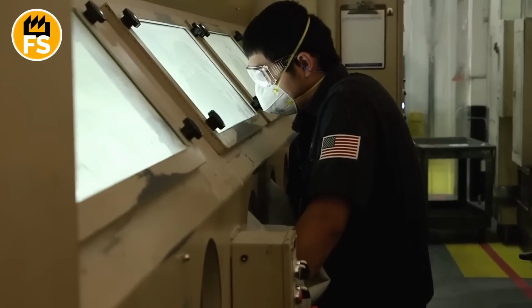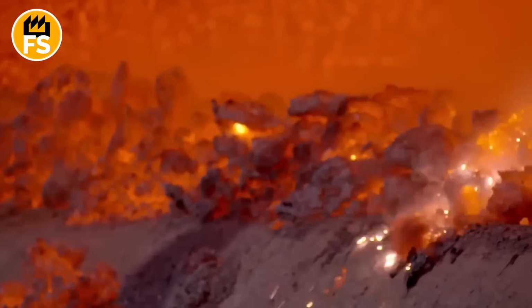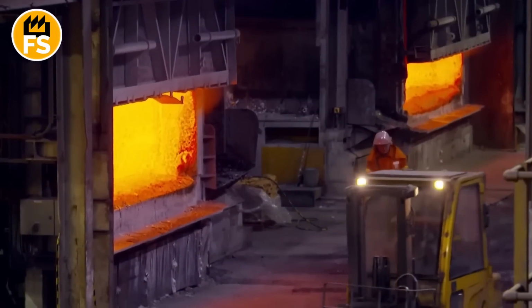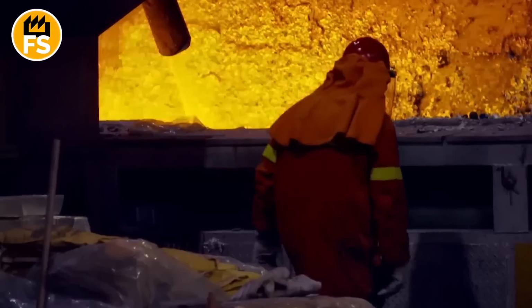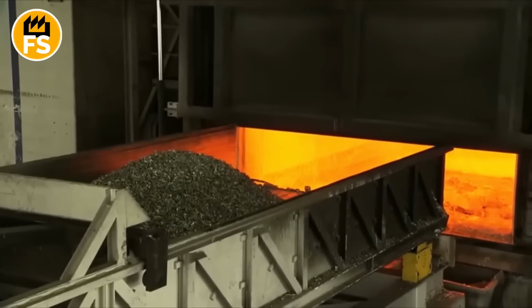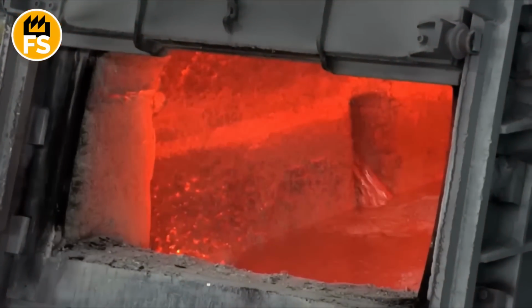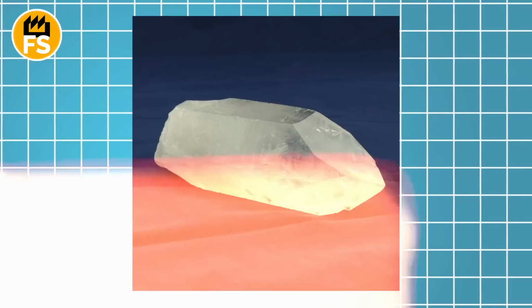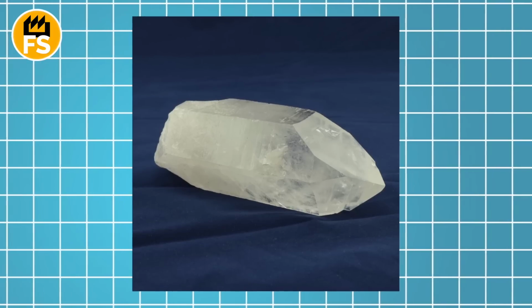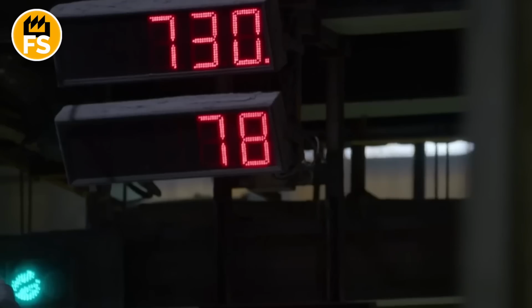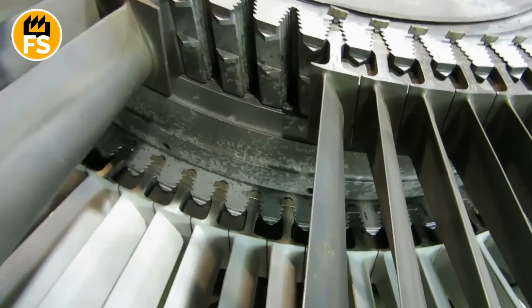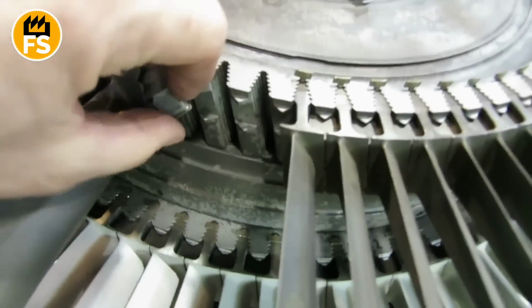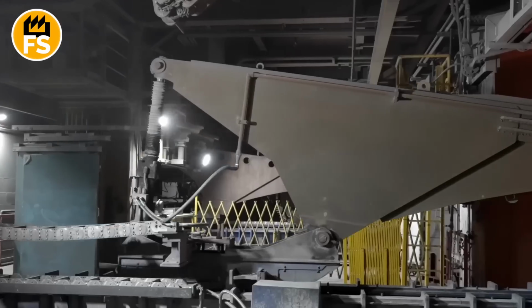Now comes the real show. Superalloys, made of nickel, chromium, and other heat-resistant metals, are melted in a special furnace to temperatures exceeding 2000 degrees Fahrenheit. This molten metal is poured into the ceramic mold. But here's the catch. It's not just about the material, it's about how it's done. To ensure the blade can handle enormous temperatures and stresses, it's often cast as a single crystal. This means the entire piece of metal has no seams, micro cracks, or grains like regular metals do. Why is this important? In these conditions, seams or cracks are like a ticking time bomb. One small flaw, and the blade fails.